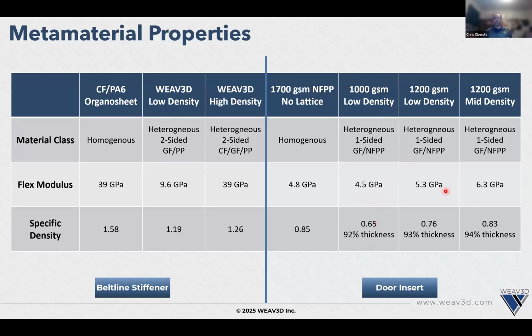And then when we look at the 1200 GSM version, slightly higher, 5.3, still 0.76, less than the original 1700 GSM. And then when we go to the mid-density version, we get to 6.3. So the key thing here is that these are all glass natural fiber nonwoven. So natural fiber nonwoven mat, glass polypropylene lattice. All we're changing is how much lattice is in that given region. And you can see you can basically tune that to whatever you'd like, from the single-digit GPAs all the way up about like the belt line into 40, 50 GPA.